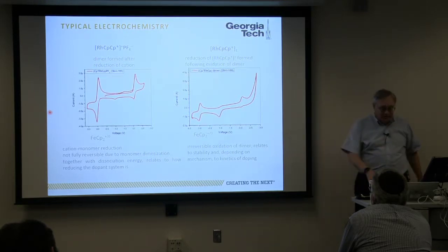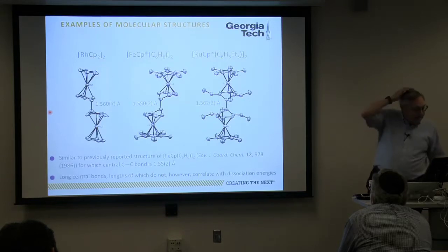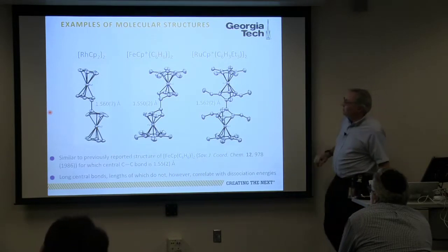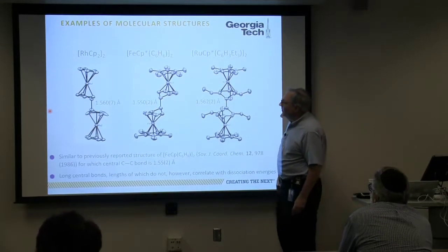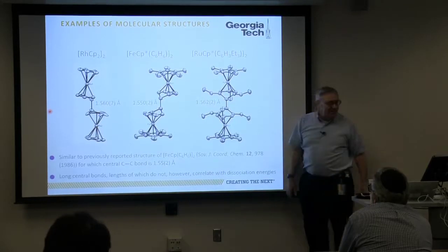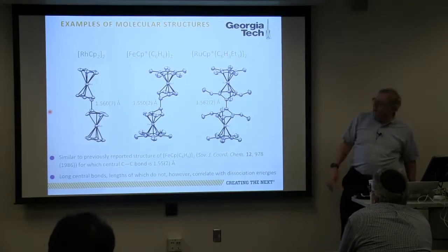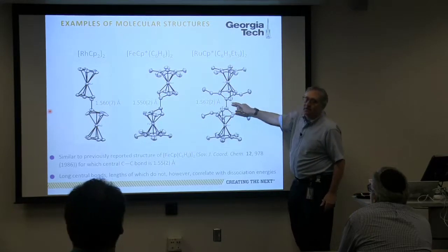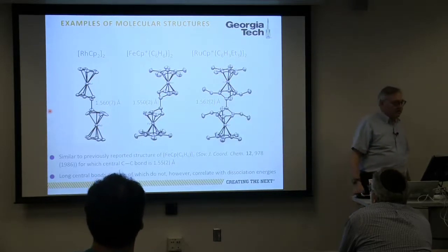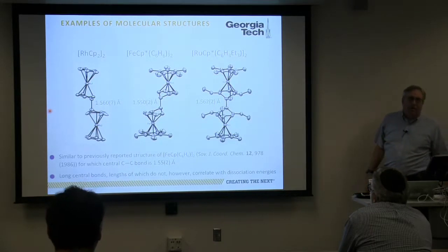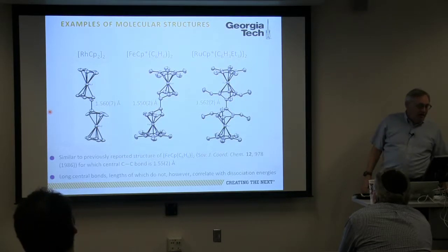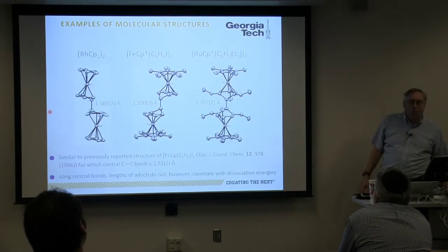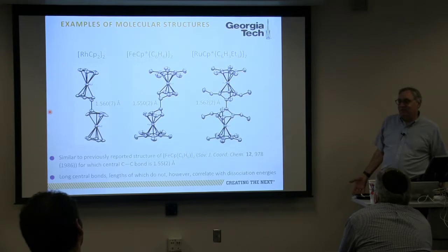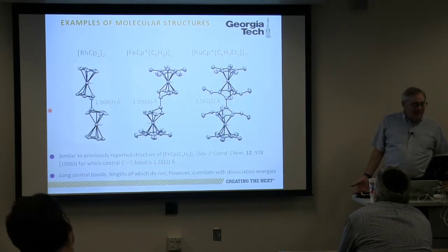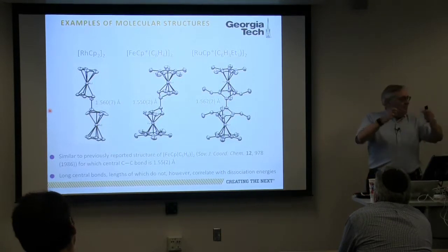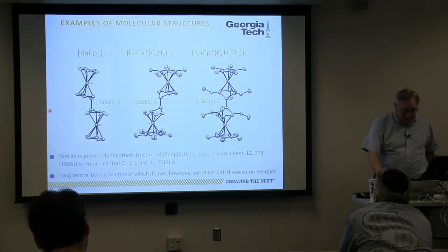is very quickly oxidized. Now, you might get some insight into this by looking at the crystal structures which we have. What I'll point out is that the single bond lengths in these molecules are very, very long for normal organic molecules. A normal organic molecule will have a bond length of about 1.54 angstroms, and these are almost a tenth of an angstrom longer. That may be associated with the fact that the bond is weaker.